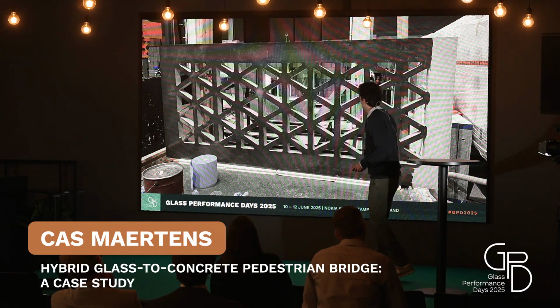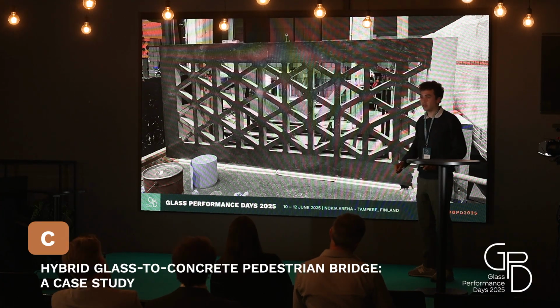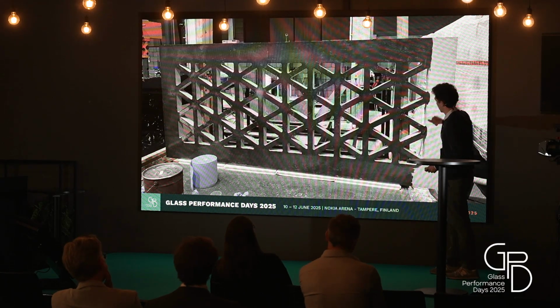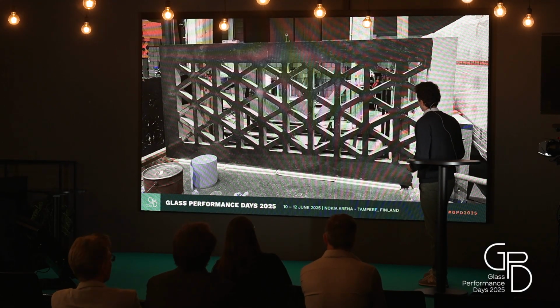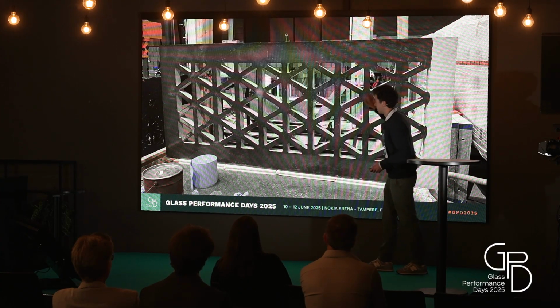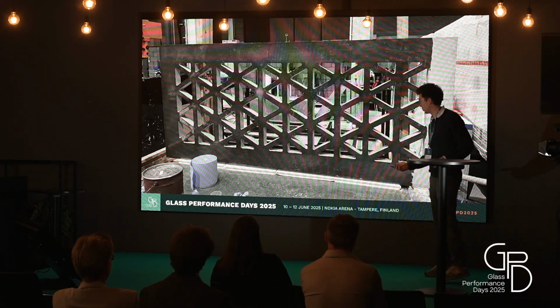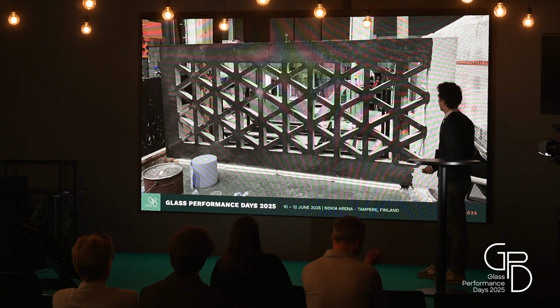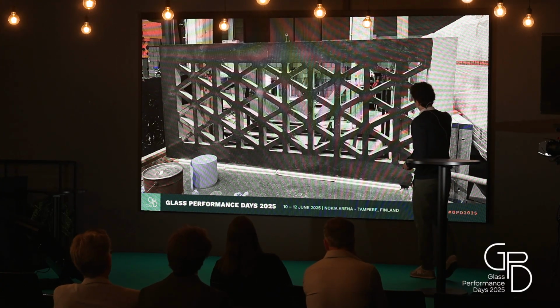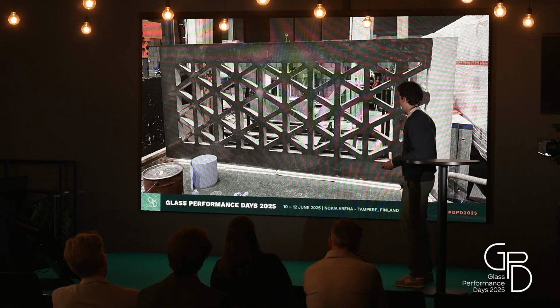And then the last point. This was the hybrid panel, and the darker area is where the adhesive comes in contact with the concrete. It becomes very dark because this is normal concrete. If we would just tape off this side on the dry concrete and then pour in the adhesive, we would have a darker color on the inside and a lighter color on the edges, which would not be favorable. As a result, what we needed to do was firstly coat the full bonded area with adhesive, so we already got this darker color, and then place the transparent spacer tape. So we would have a uniform look.